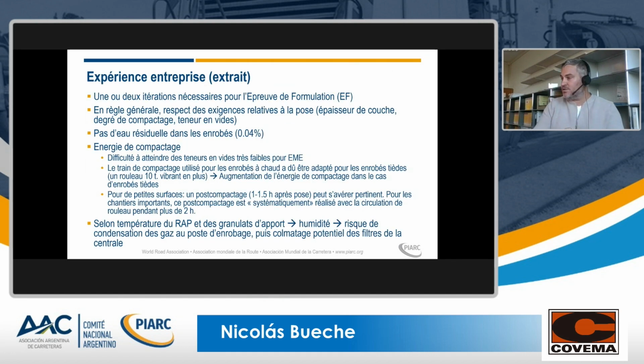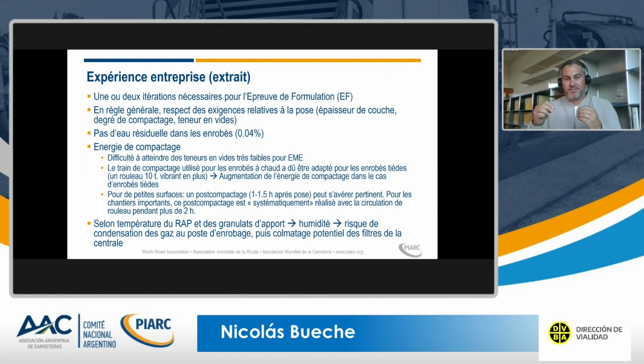So just a short summary also from a more practical experience from the laying company. What we could observe, first for the recipe, we needed 1 or 2 iterations just to make sure that, the tricky point was really the fatigue and stiffness, that we can meet both criteria at the same time. Then a very important control point, the humidity, the water content of your asphalt mixture.